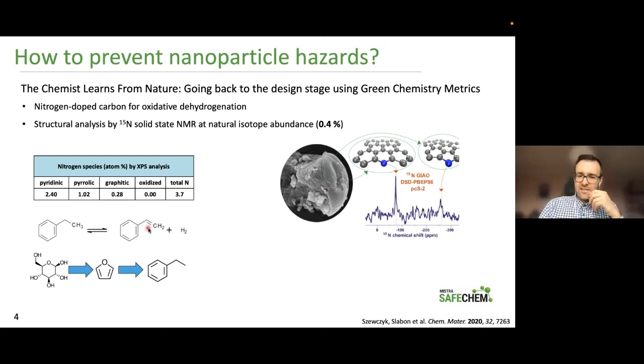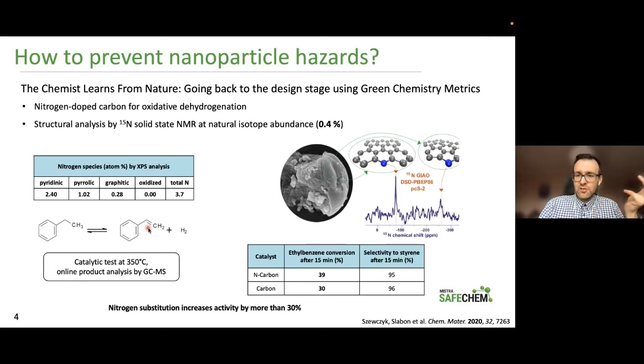And this catalyst doesn't have any nanoparticles inside, and it's quite efficient for this reaction. Basically, you have, first of all, no leaching of nanoparticles because you have a benign material. And if you introduce the nitrogen here, you can increase the catalytic activity for this dehydrogenation reaction by 30%.